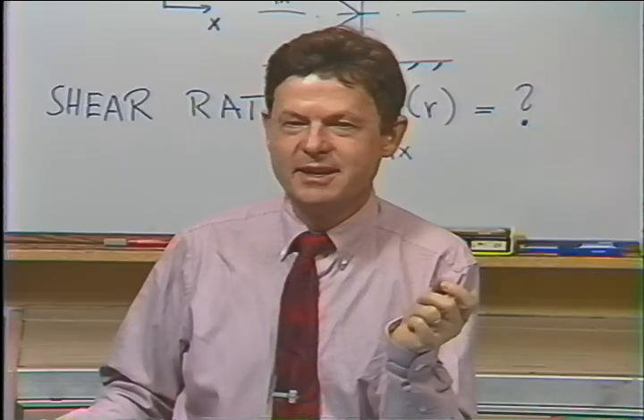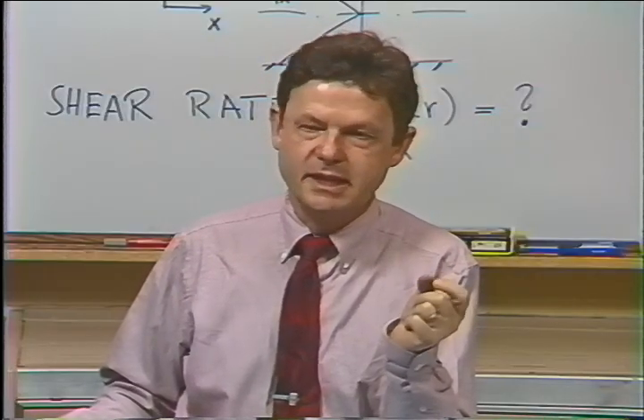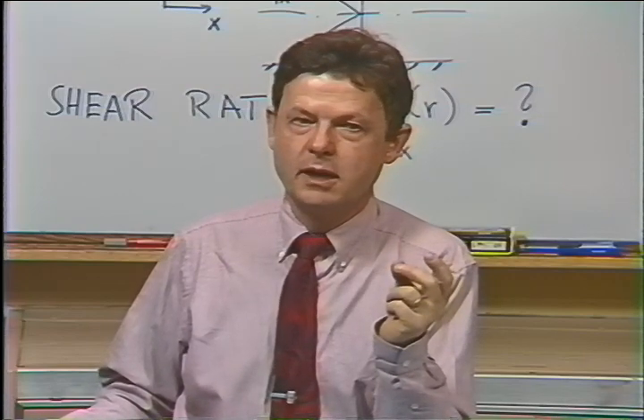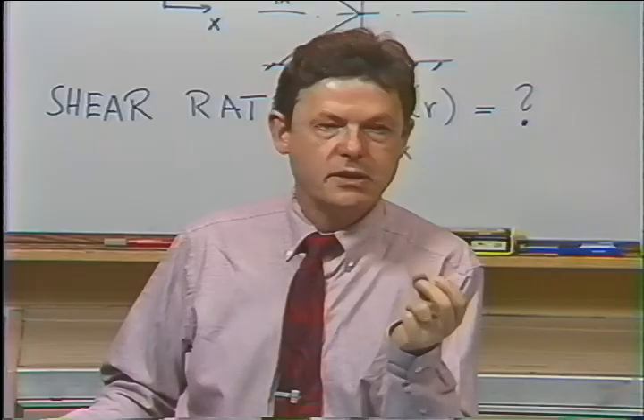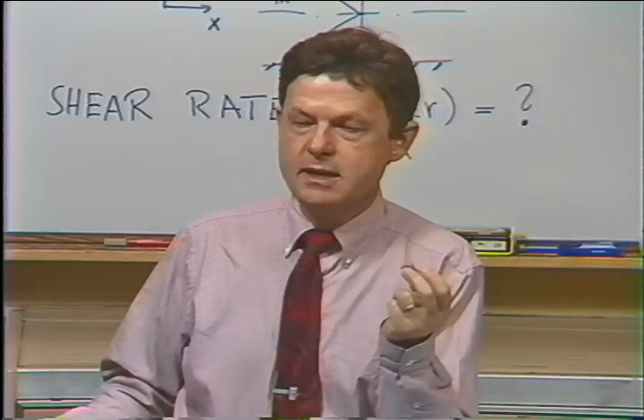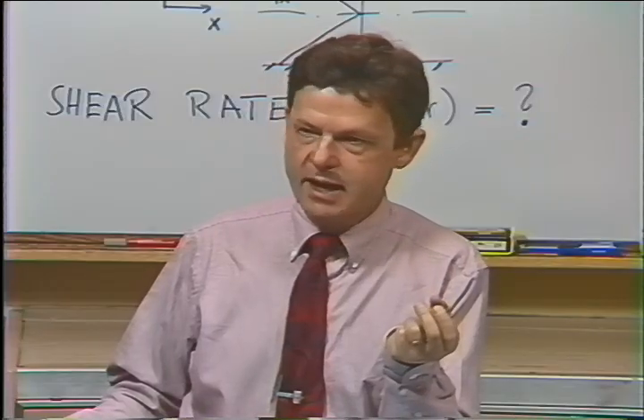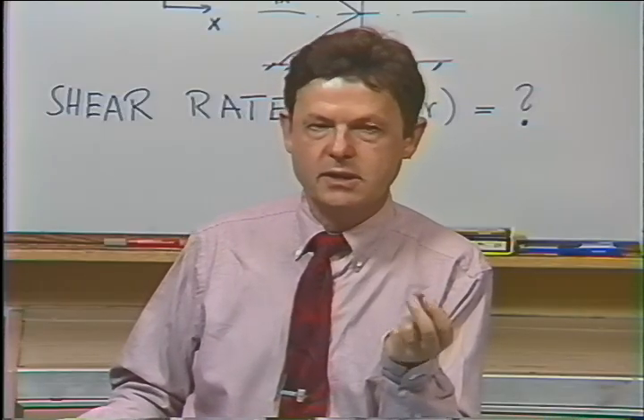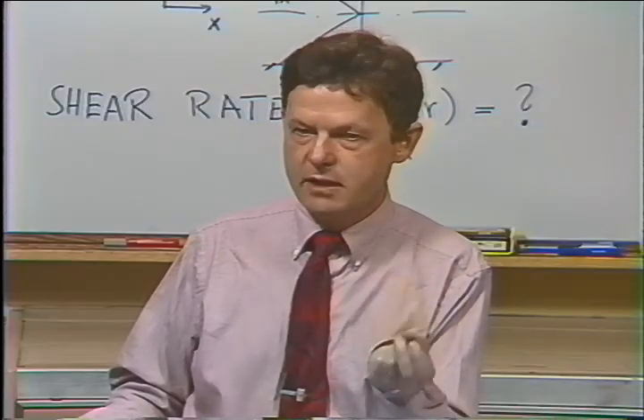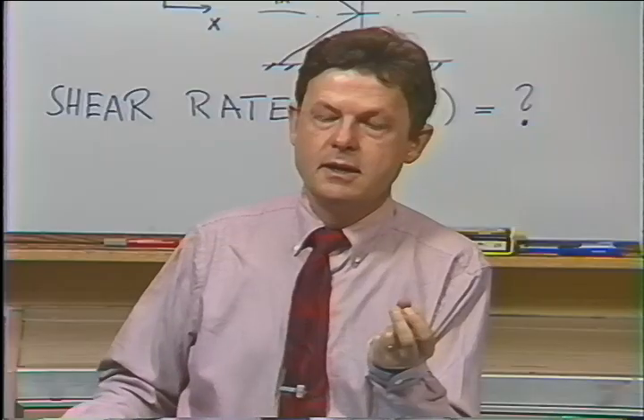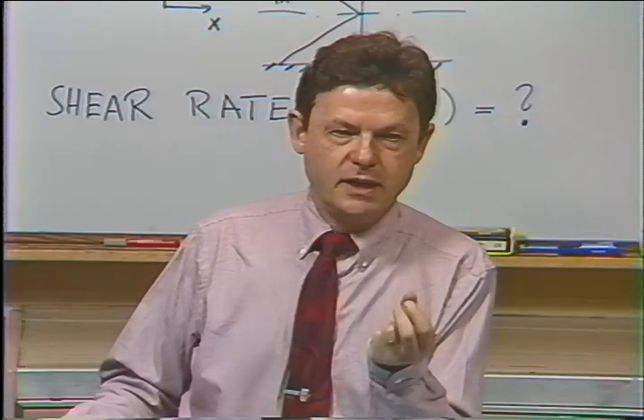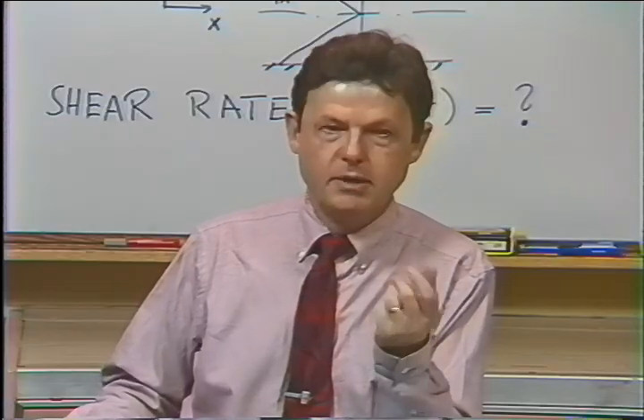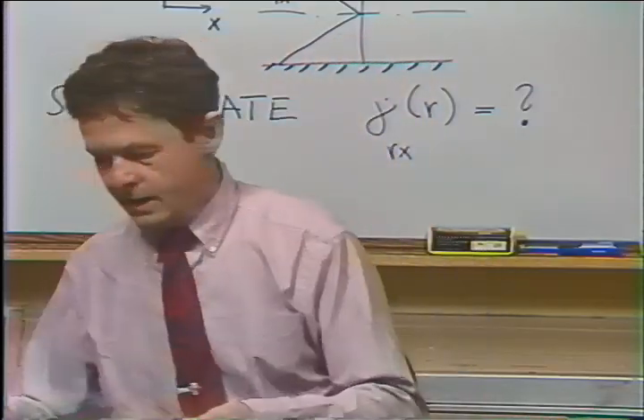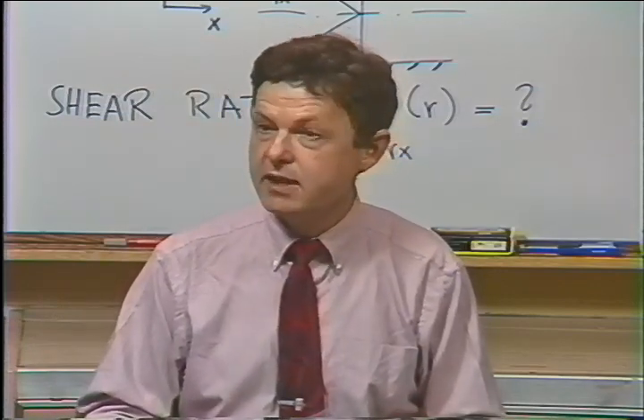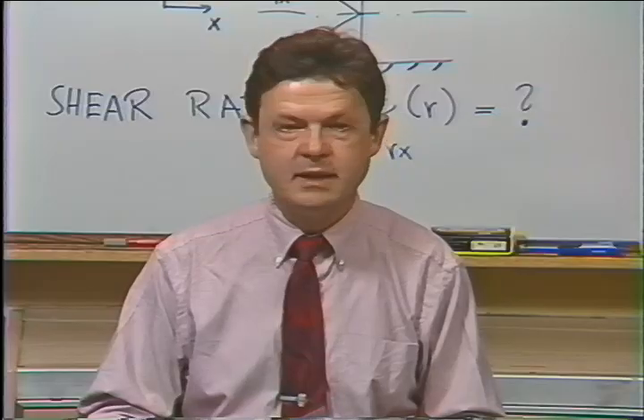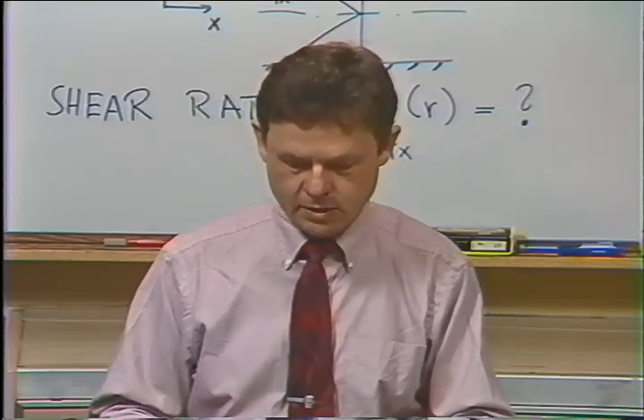Now I want to shift to a new aspect of capillary rheometry, and that's viscous heating. Normally, capillary rheometry is used for measuring material functions at very, very high shear rates. And the viscous dissipation is very high. The rate of this viscous dissipation is equal to the stress times the instantaneous rate of deformation. So that's the local rate of heating per time and per unit volume. And that will change our experiment. We will not have isothermal conditions. So what can we do to maintain isothermal conditions or to keep viscous dissipation low?